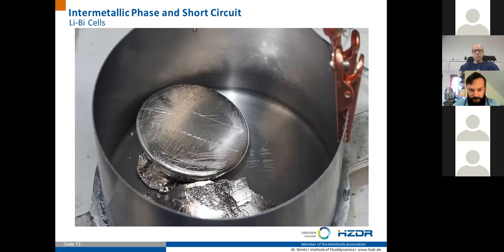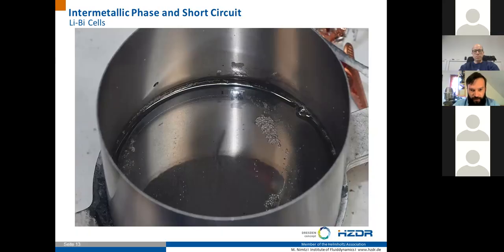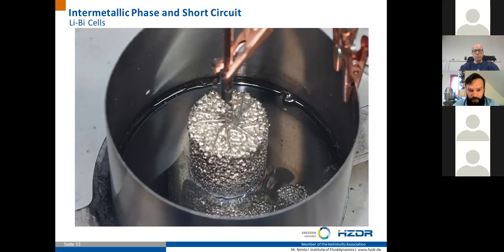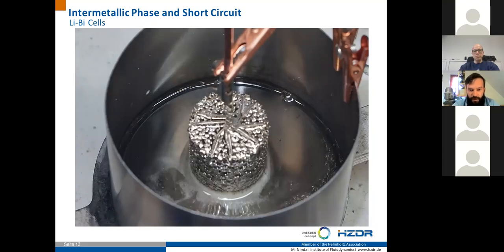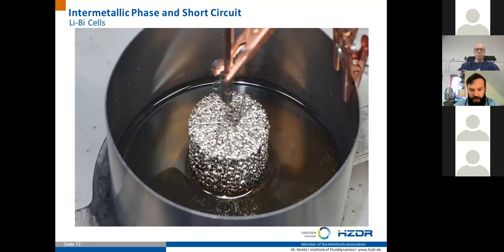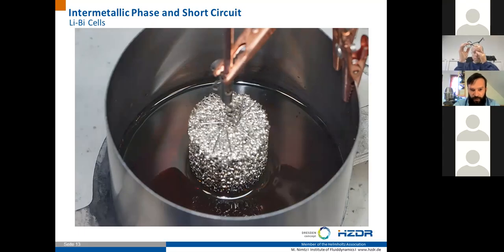Here, I'd like to show how this could look. These are the pictures I've already shown. What happens when we lower the electrode can be, for example, something like this. During the first contact, you can see lots of very small gas bubbles forming in the electrolyte. This could be a side reaction. Then you will see some change of color over time. Here we have a somehow greenish color of the electrolyte, which over time might switch to a dark red color, and this indicates a solution of the intermetallic phase in the electrolyte, which is also something you usually do not want to have in such a cell.